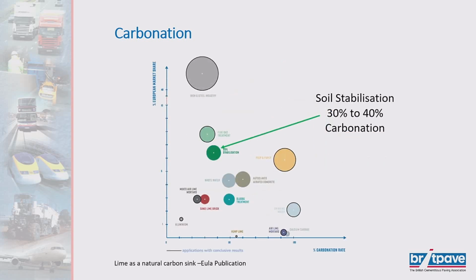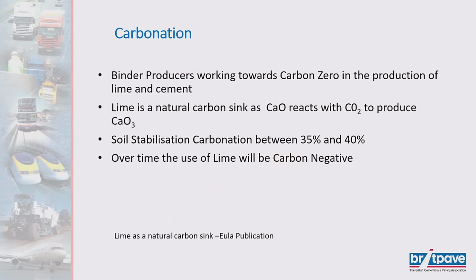But on this basis, soil stabilisation has a carbonation rate of 30 to 40%. It puts it back in. And going forward, others will talk about this later, binder producers, both lime and cement, are working towards carbon zero in terms of production of that material. So lime itself is a natural carbon sink as it reacts. So soil stabilisation carbonation, 35%. So over time, the use of lime and other materials will actually be carbon negative because of the nature of the process. If they can produce binders with zero carbon, with carbonation, it becomes a carbon negative product in terms of using soil stabilisation.